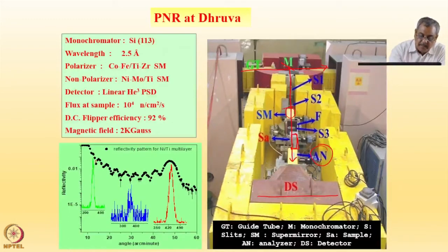Each experimental point at q-space is actually an integration over an intensity profile on the position sensitive detector. We also take the background channel-wise on the PSD after closing down the sample with a cadmium slit. Cadmium is a strong neutron absorber, so we don't allow anything to come from the sample onto the detector. That tells us how many stray neutrons are there in the guide hall, which is much smaller than in the reactor hall.